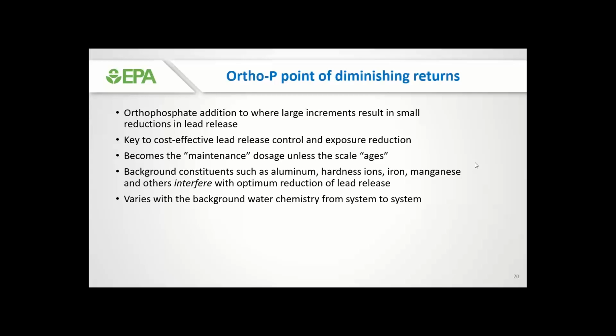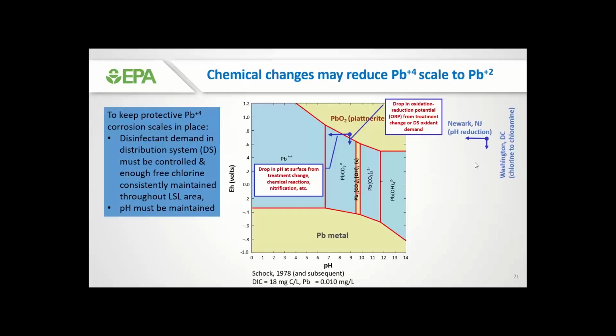But do keep in mind that these background constituents that we mentioned before that can make up scales, such as aluminum, hardness ions, iron, manganese, and others, may interfere with that orthophosphate concentration, and we may actually need more if there's a thick pipe scale layer there instead of a fairly smooth, clean pipe. So the point of diminishing returns for orthophosphate will vary with the background water chemistry and with the makeup of the scale from system to system. Even if we are in a pretty good condition where we have passive scales forming, we really need to maintain the conditions that created those stable passive scales to begin with.